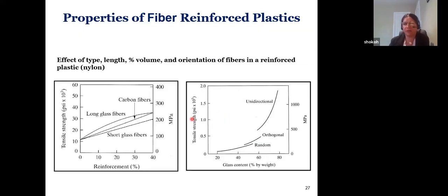So I showed the example. Here I have a tensile strength, based on PSI, and I'm applying stress to, for example, a material with carbon fibers, like a plastic or nylon resin with carbon fibers. You see the behavior as I change the percentage of reinforcement from 10 to 30. Carbon fibers give me, for example, less than 30 strength. If I use the same material, nylon, with short glass fibers, it gives me less, and if I use long fibers, it gives me higher. So the type of fiber impacts the property. If I change the length of the fiber, or increase from 30 to 40, it will also change.